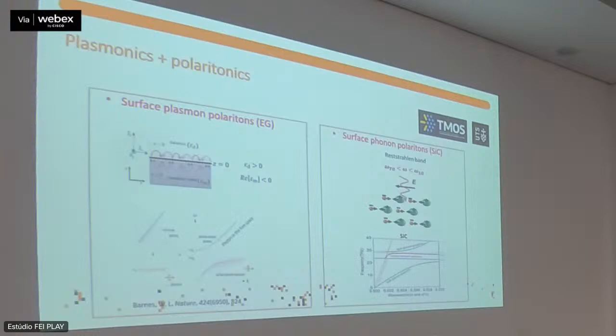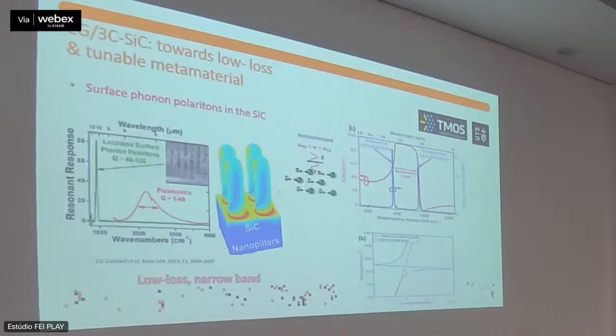And this is quite interesting because you can use it like you can use plasmonics, but in the mid-infrared. But at the same time, we have graphene. And what happens is that we can actually try and combine the two. So this shows you that silicon carbide alone can be a really low loss material. When you use plasmonics like silver and gold, you would have a lot of losses inside those materials, so you would have much lower quality factors and much more spread. But with silicon carbide you only have a very narrow band, a strong band, and you can't really move it.